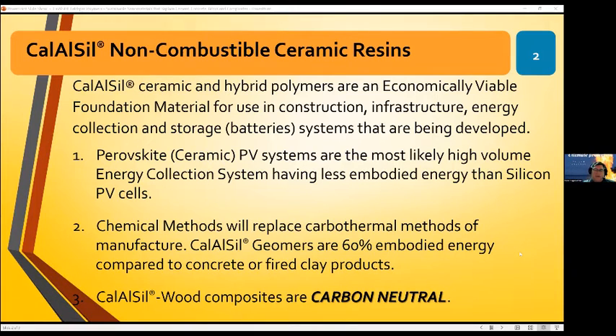The primary difference is that I begin with a silicate resin. That resin is essentially a hydrolytic binder of particles, and allows the particles to coalesce together in a much more ordered and much more structured manner. This allows for higher strengths just through simple evaporation of the solvent, which in this case is water.